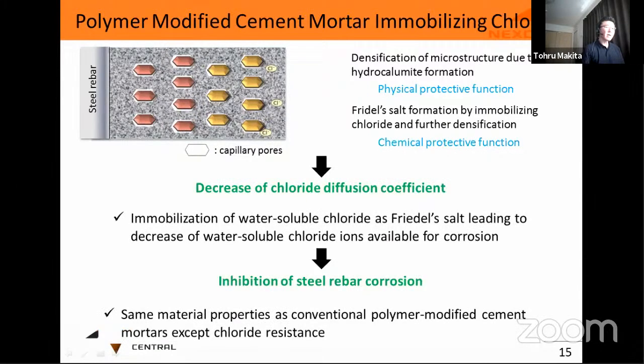So to summarize, formation of hydrocalumite and Friedel's salt densify the microstructure of repair mortar, eventually bringing about a decrease of chloride diffusion coefficient, and formation of Friedel's salt decreases water soluble chloride ions available for corrosion and eventually inhibits steel rebar corrosion.